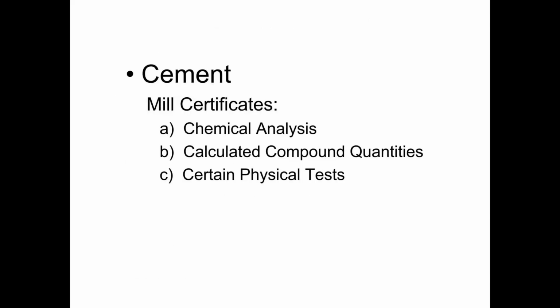Generally, we're going to use our mill certificates to give us an indication of whether or not the cement is meeting the desired parameters. Generally, the mill certificates indicate a chemical analysis that includes compound quantities for the different oxides that are present, and it also gives the results of physical tests. ASTM C150 is the primary ASTM that is used to govern the requirements for cement. And so generally it's going to be ASTM C150 requirements that we would be referencing back to. The mill certificate we would expect to state explicitly that the material represented meets ASTM C150 requirements.